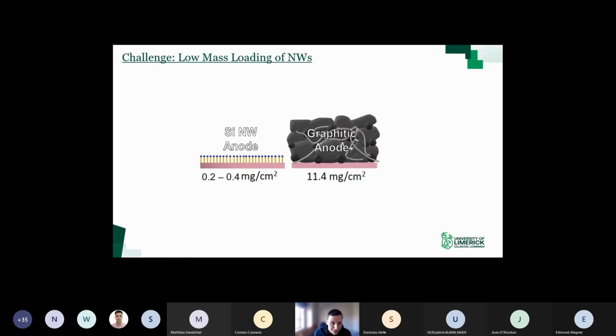Okay, so that's the SEI layer, and the last major challenge then is the low mass loading of nanowires. If we look at a commercial graphite electrode, typically they have a charge storage capacity of about 4 milliamp hours per centimeter squared, and that would correspond to about a mass loading of 11 milligrams per centimeter squared of the graphite. If you want to just match that with silicon, and if you assume that your silicon is going to deliver a capacity of 2,500 milliamp hours per gram, you would need a mass loading of silicon nanowires of about 1.6 milligrams per centimeter squared.